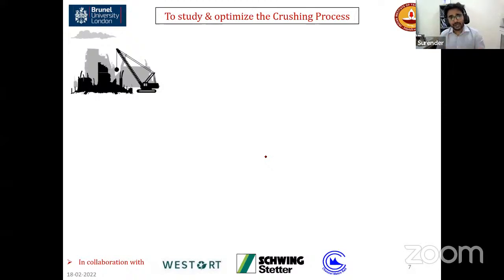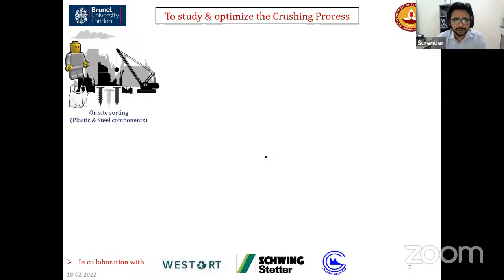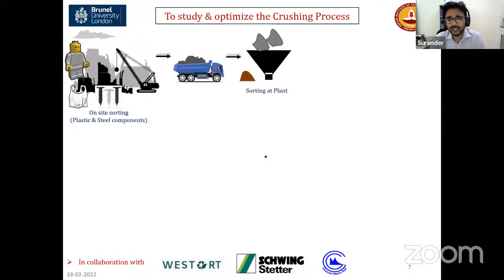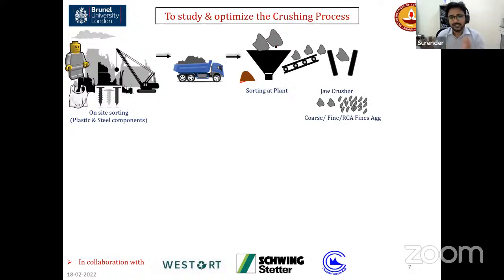So we thought, okay, we'll start with the base, right? Normally, all across the globe, when a building or any other concrete infrastructure is demolished, manual sorting happens. Most of the time, plastic and steel are sorted during the demolition stage only because they have high residual value. Then they are brought to the recycling plant, where, because some soil fractions, excavated soil, will also be there, we can vibrate it so that we can remove the soil from the recycled concrete chunks. And then mostly, with the help of a jaw crusher, we resize the aggregates into coarse aggregate and fine aggregates.